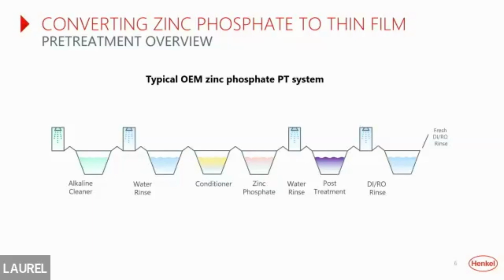So let's start with a typical OEM zinc phosphate system. This may not look exactly like yours, but it's kind of a generic version. We've got our cleaning stages first. They're alkaline cleaning stages, a spray and an immersion stage, followed by water rinses, usually 2, followed by a surface conditioner, which activates the metal, gets it ready for a zinc phosphate coating, which happens in the next stage. The conversion coating takes place here, followed by a water rinse, maybe 2.